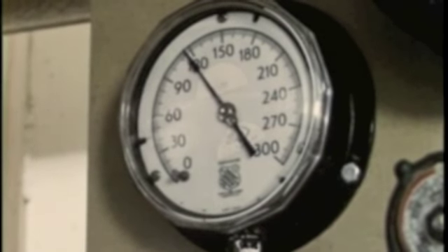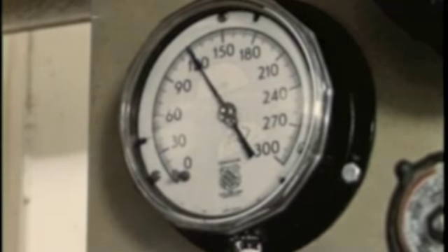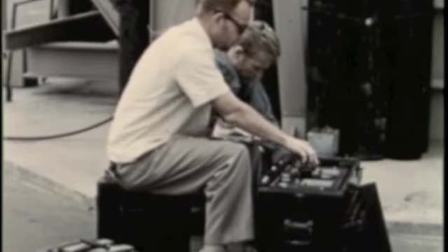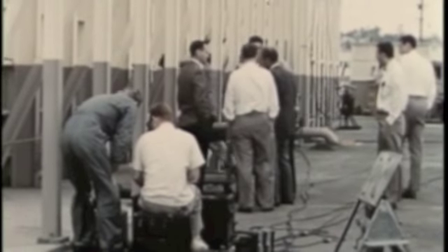Pressure continues to increase until firing level is reached. The glass fractures, but it does not shatter. In this test, the dummy showed no damage to his simulated human tissue. Here is the same test in slow motion from the pilot's point of view. Although in this test the windshield passed satisfactorily, Convair engineers prefer a newly developed laminated shield being tested now.